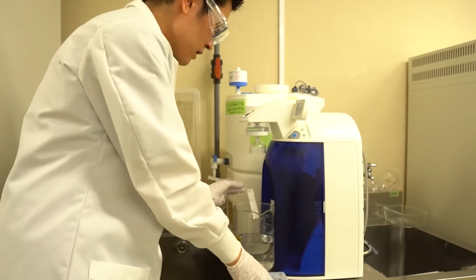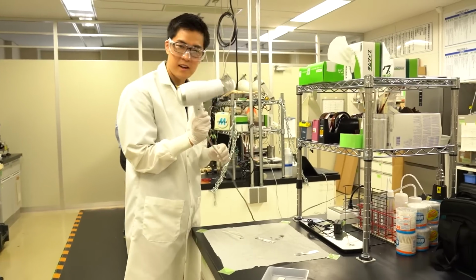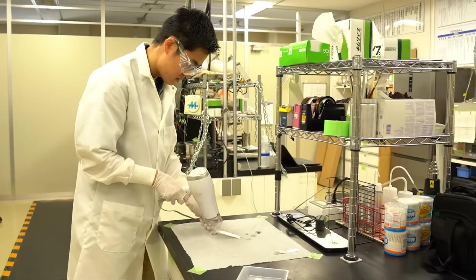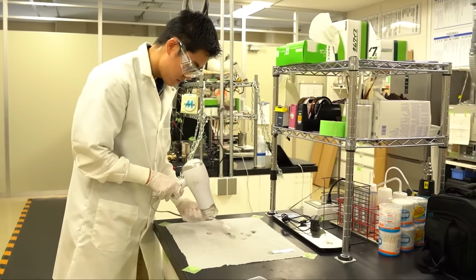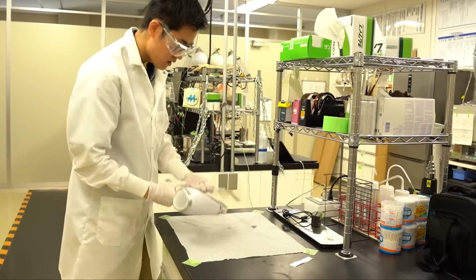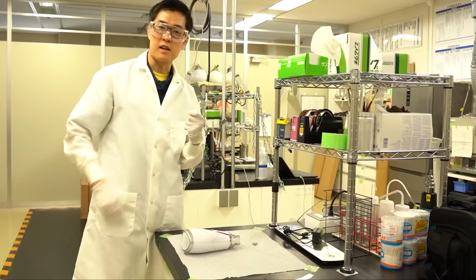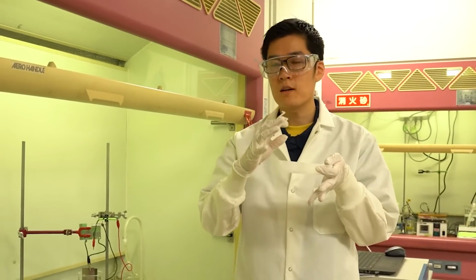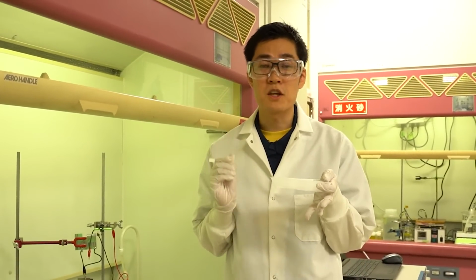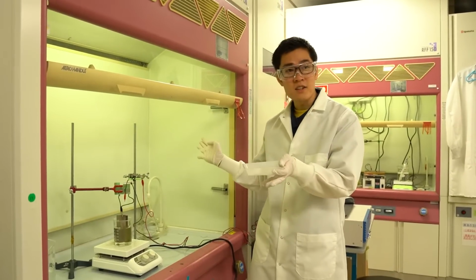I'll rinse the surface with pure water. It's done. If you proceed to the next step right away, the water on the surface of the aluminum foil will affect the composition of the chemical solution in the next step. It's completely dry. Now pre-processing is completed, let's go to the next step. Once the aluminum foil gets cleaned, you need to quickly move on to the next step before it forms oxide on its surface. Here, I'm going to etch the aluminum foil.